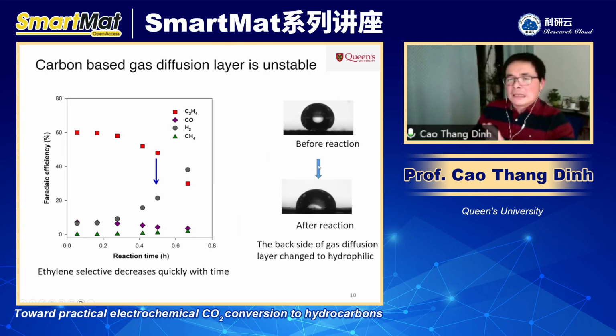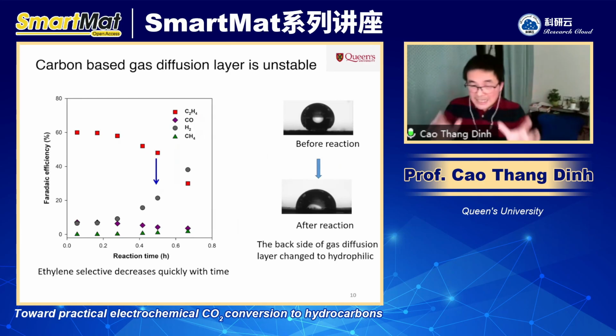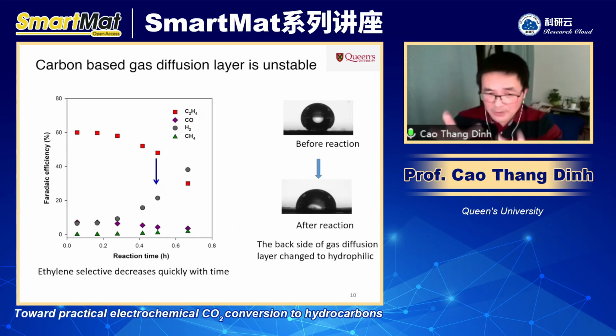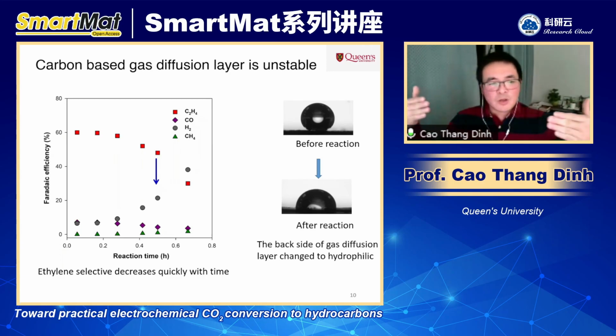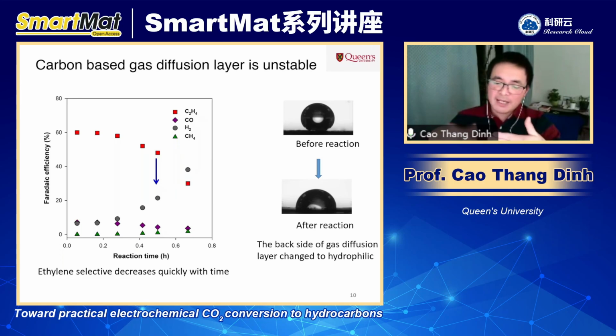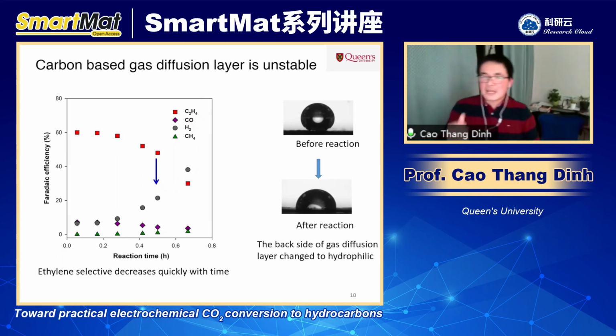And when we looked at the back and the front of the gas diffusion layer, we found that it turned from hydrophobic into hydrophilic, right? There are different mechanisms for why the carbon changed from hydrophobic to hydrophilic. But the bottom line is that now the porous layer becomes hydrophilic, and then the water penetrates inside the pores of the gas diffusion layer, and it blocks the diffusion of CO2. Now you do not have CO2 reaching the surface of the catalyst, and that's why we do not have CO2 for the conversion, and we produce hydrogen.